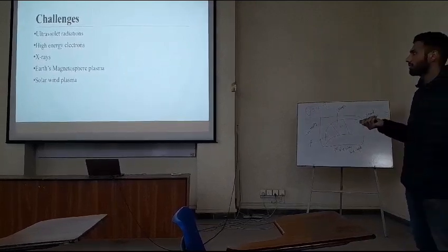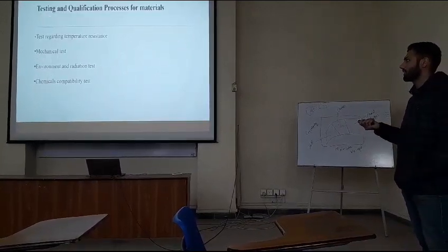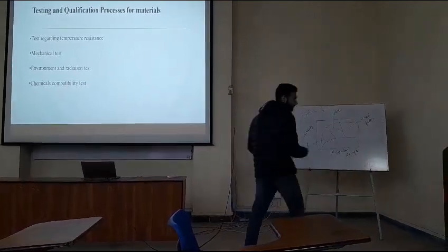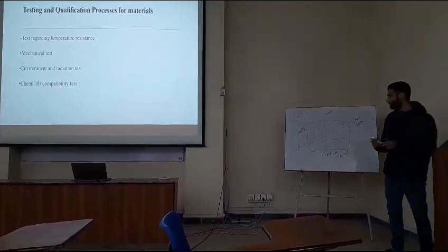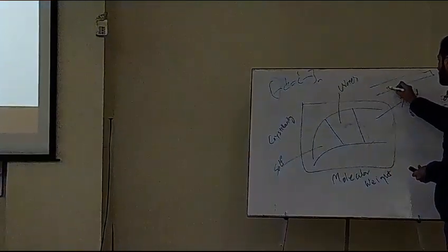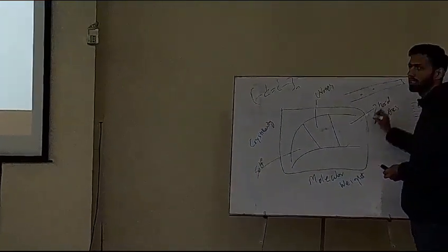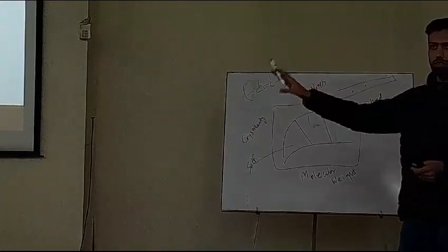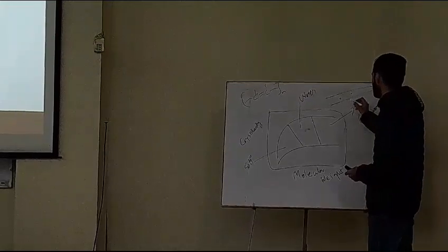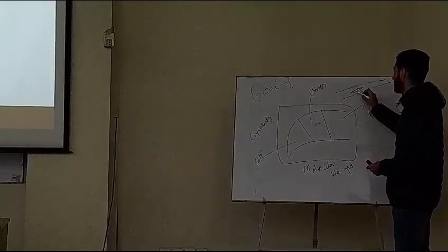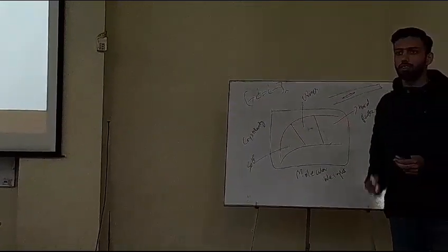There is a picture that I didn't add that showed the sheet. You can add that picture in your paper, okay? So basically this was the Kapton sheet, and some holes would start to appear over time because of the ultraviolet radiation and high energy electrons. After some time, these holes would connect, and this Kapton material would have a huge cavity inside. And this is damaged.